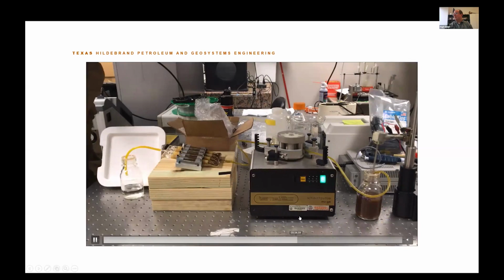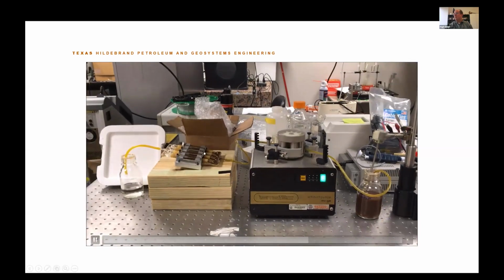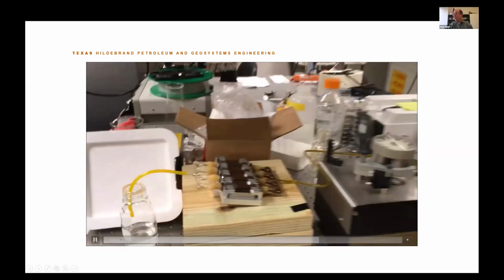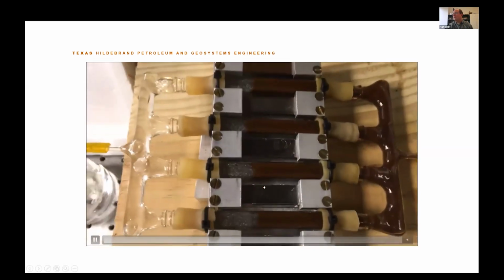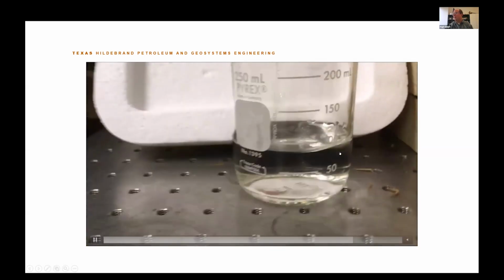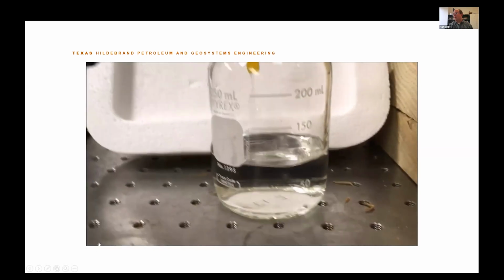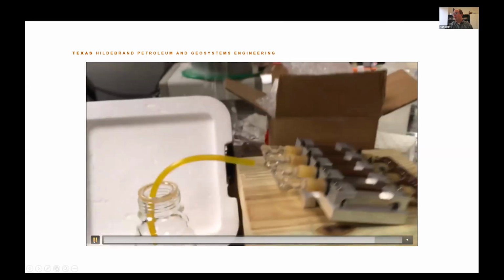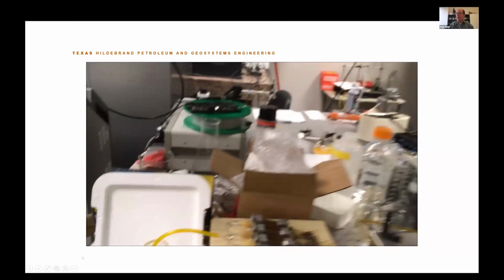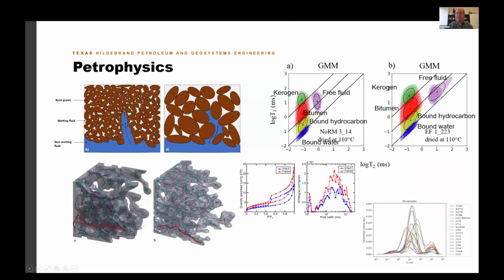Okay, and then we turn on the pump and we run them through this magnetized battery of, this is steel wool that's in these tubes. And the magnetized steel wool picks up the oil droplets, and what comes out on the other end is clean water. And so we're able to remove like 99.7% of the oil droplets that are there. So it's pretty cool stuff.